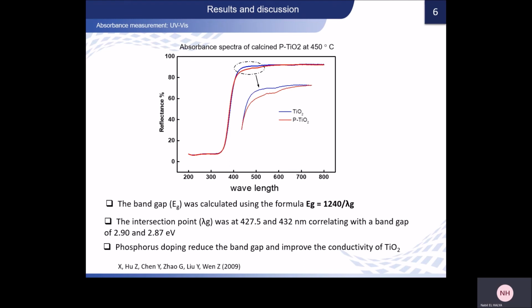For the absorbance measurements, compared to pure anatase, it is observed that the phosphorus doping extends the wavelength response range into the visible light region. The band gap of titanium dioxide and P-doped titanium dioxide was 2.9 and 2.87 electron volt respectively. This result confirms the effect of phosphorus doping to reduce the band gap and improve the conductivity of titanium dioxide.